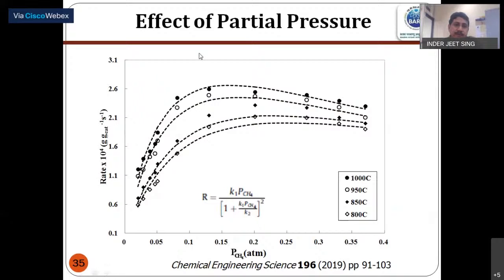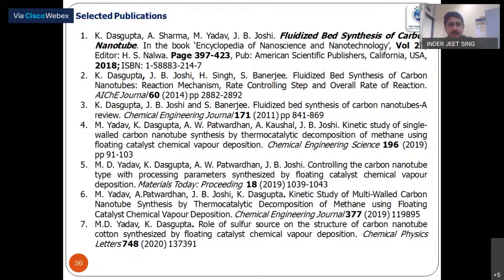Now, if we see the effect of the partial pressure, if you remember, for multi-wall, generally the rate goes on increasing and becomes slow, but it goes on increasing. But in the case of single wall, there is a drop in the rate of formation. Typically it follows a different model. So that is why we always synthesize single wall carbon nanotube at a low partial pressure, and we cannot scale up the single wall carbon nanotube production. The rate of production cannot match the production of multi-wall carbon nanotube. So these are some of the selected publications that we made.